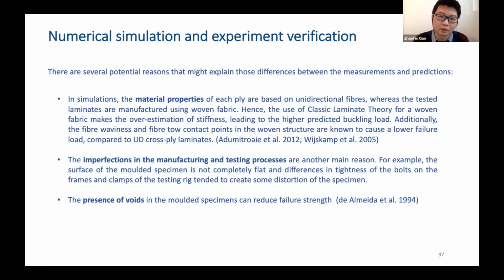There may be three different reasons to explain that. The first one is material properties, because in the simulation we use the material properties of the unidirectional fiber, whereas when we manufacture the laminates, we use the woven fabric. And also imperfections in the manufacturing and testing process will cause this difference, because maybe the surface of the molded specimen is not completely flat, and the difference in tightness of the bolts around the frame and the clamps may create some distortion to the specimen. And also the voids in the specimen can reduce the failure strength.